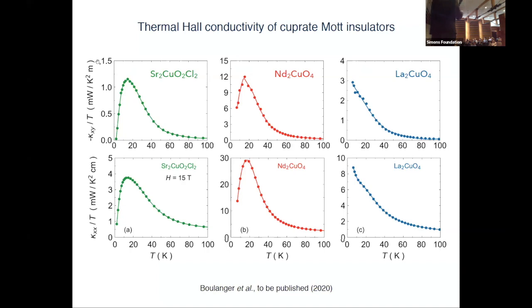But just to come back, my view is that we have to re-examine all measurements of thermal Hall in insulators. In particular, thermal Hall is used in spin liquids as a potential probe of exotic particles like Majorana fermions and anyons. But it seems very likely to me that there's going to be a phonon signal in those systems as well. So, for example, getting a quantized value is very unlikely because you'd have to have zero phonon contribution.